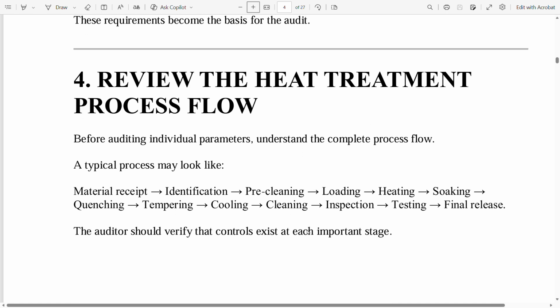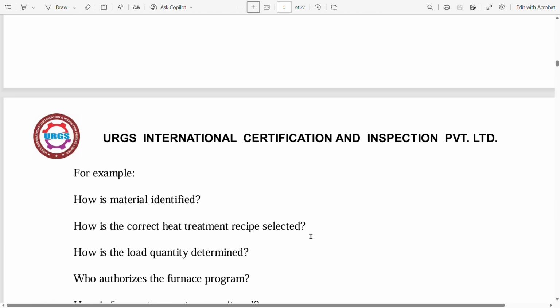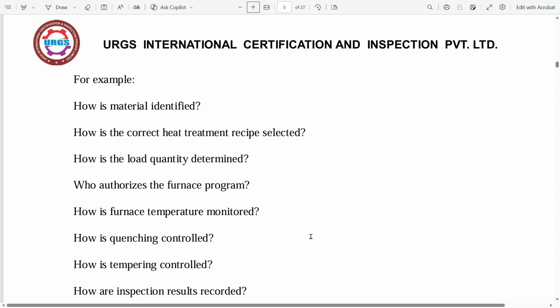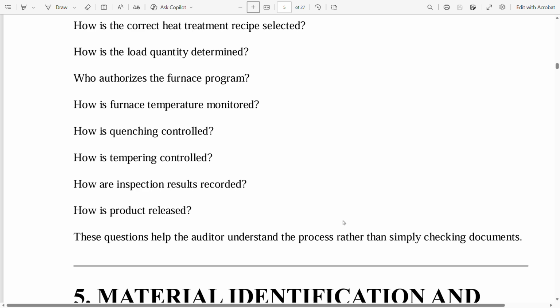Then next is reviewing the heat treatment process flow. Before auditing individual parameters, understand the complete process flow. A typical process may look like material receipt, identification, pre-cleaning, loading, heating, soaking, quenching, tempering, cooling, cleaning, inspection, testing, final release. The auditor should verify that controls exist at each important stage. For example, how is material identified, how is the correct heat treatment recipe selected, how is the load quantity determined, who authorizes the furnace program, how is the furnace temperature monitored, how is quenching controlled, how is tempering controlled, how are inspection results recorded, how is product released. These questions help the auditor understand the process rather than simply checking documents.